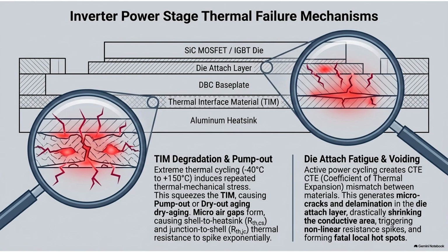And the material it's made of, silicon carbide, is crucial here. Traditional silicon chips would just melt at the power levels required for modern EVs. Silicon carbide is a much more robust, wide bandgap material that can handle massive voltages and higher temperatures. But even with silicon carbide, there is still resistance. I mean, it's not a perfect superconductor. Right. Every time that valve opens and a massive surge of current rips through it, the electrical resistance of the material creates instantaneous, intense heat.